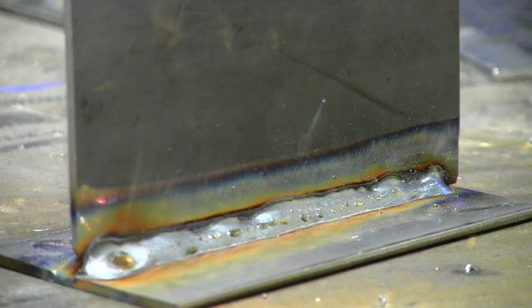So what I want you to see is that this is a balancing act between wire feed speed and voltage. And so this had the same effect as if we would have left the wire feed speed the same and yet turned the voltage up to 29.5 volts. Okay, now I have the wire feed speed at 700 inches per minute and the voltage at 27.5. And so now we're going to see what happens when the wire feed speed is turned up and the voltage is left the same from our optimum setting.